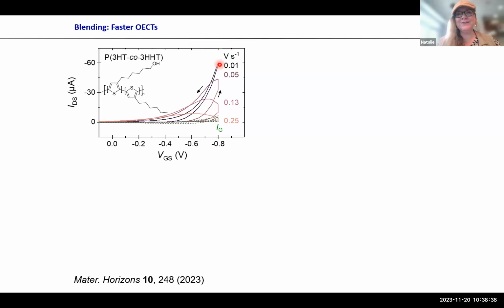And I have to say the community is often a bit cheating. They, in many cases, do not give actually at what rate they measure, meaning at what rate do they change the gate bias. And if you go back here, you see if you go very slow with 0.01, you get actually a pretty decent characteristics where the forward and backward scan is sort of identical. However, if you go faster and faster, you see you get ions in, oxidizing your polymer, creating a current, but it's much more difficult to get ions out.